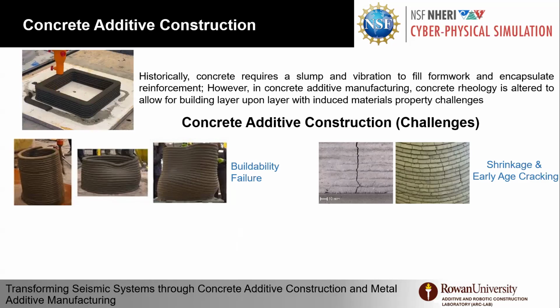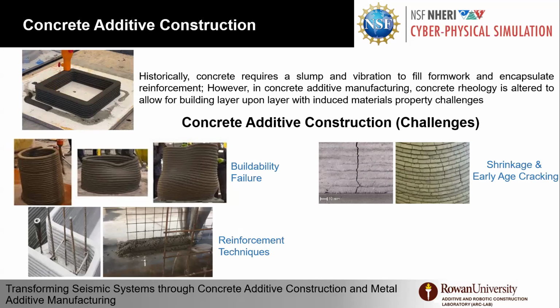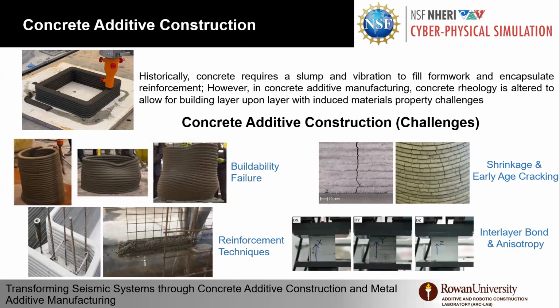Scaling this technique up, as Dr. Rickles mentioned earlier, reinforcement is a bigger challenge in this industry, because we always think of reinforcing the same way with the same rebars and stirrups, while we can have alternatives because those were driven by formwork. We also have interlayer bond issues and anisotropy due to the layer-by-layer nature of 3D printing. So you could basically have material property changes in the X, Y, and Z directions.